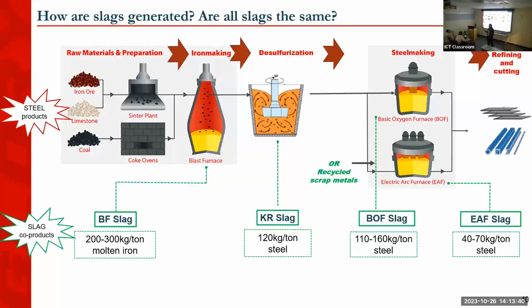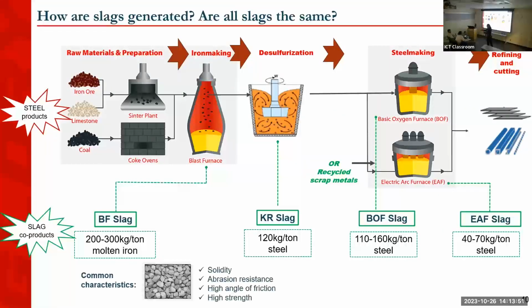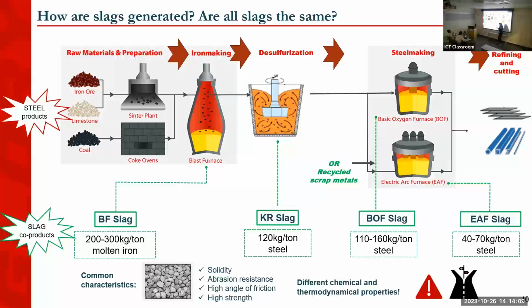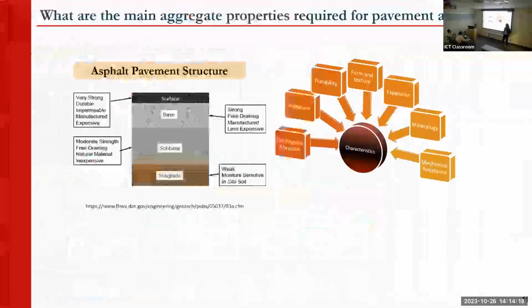Before, when people were not using slag as a pavement material, they were all blended together, very heterogeneous. So it's really important to separate the materials, like plastic. We've got to separate LDPE, HDPE, polypropylene, so we can have a better idea of the material characteristics, so we can better blend and optimize the materials. Same thing for slags. So we saw that there were different types of slags, and all of them possess good solidity, good abrasion resistance, high angle of friction, high strength. However, they differ in terms of chemical and thermodynamic characteristics.